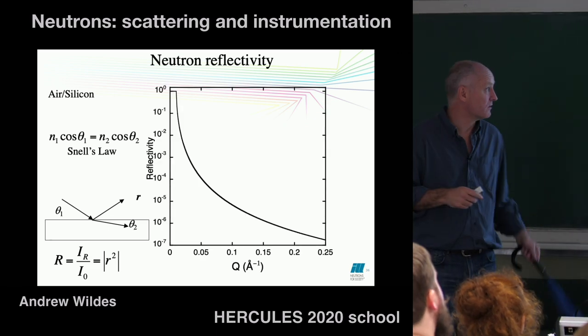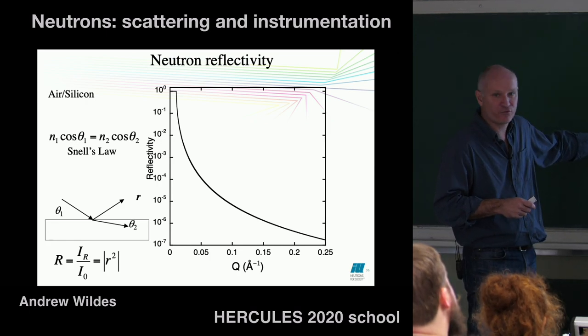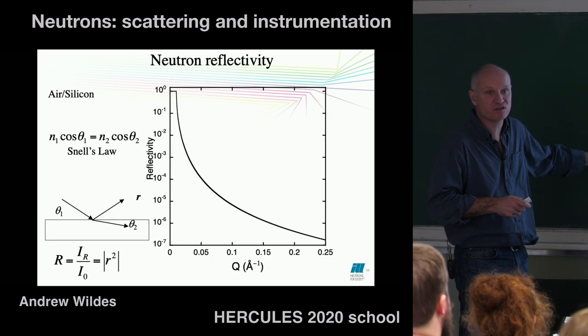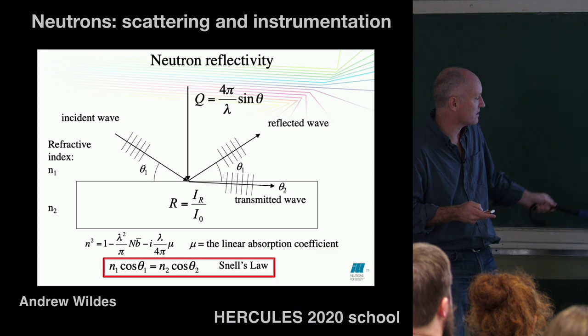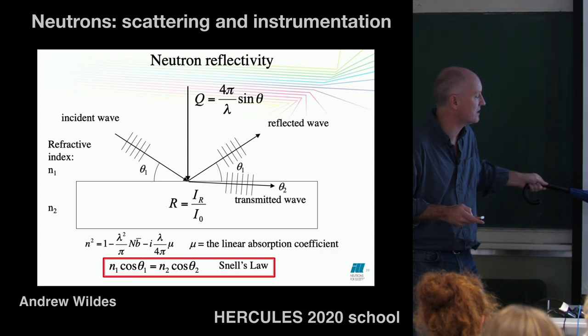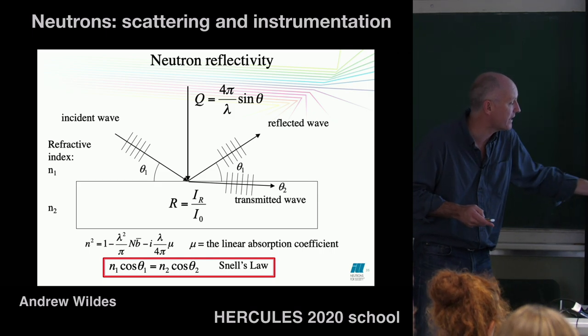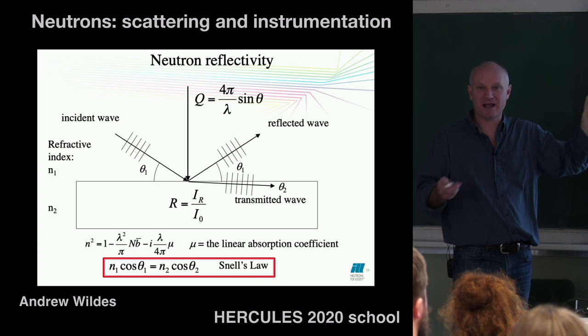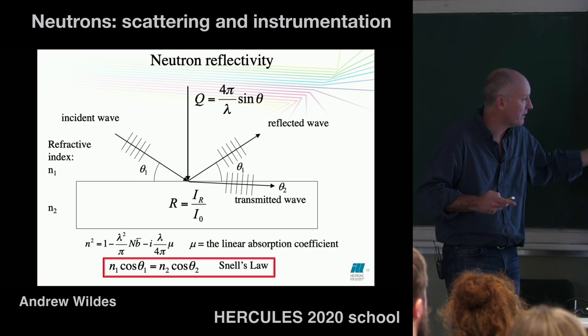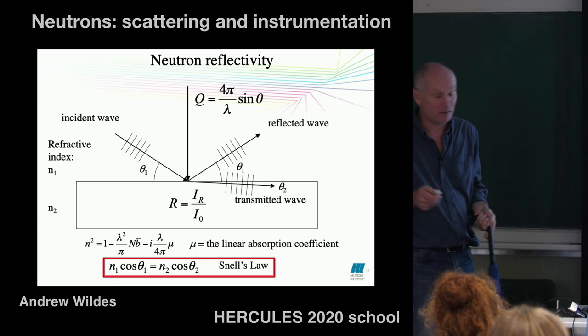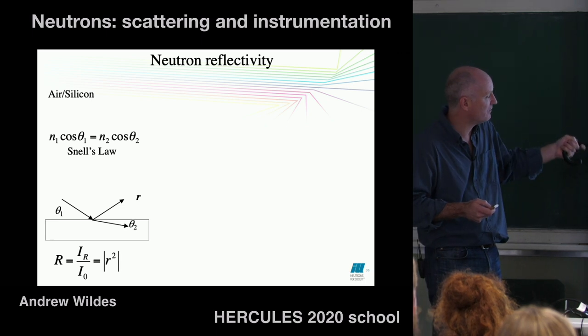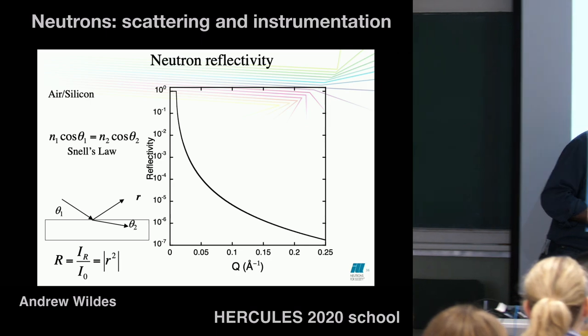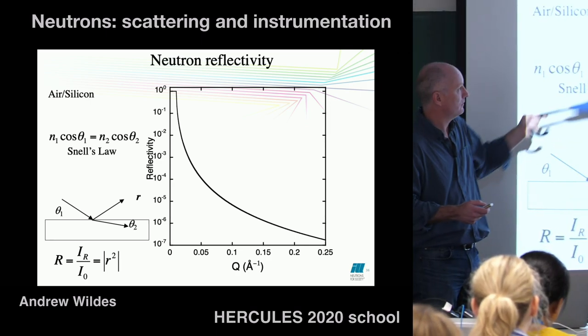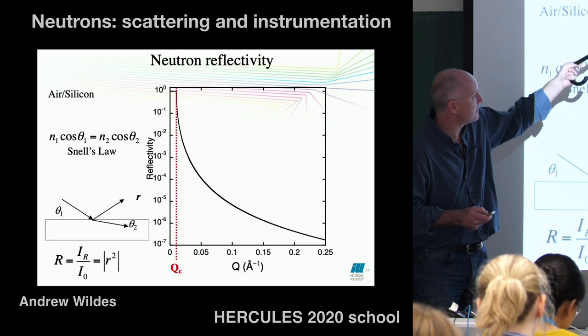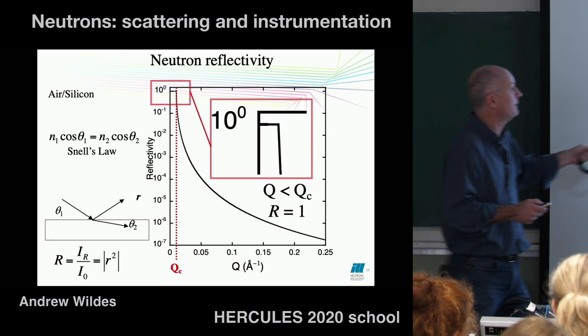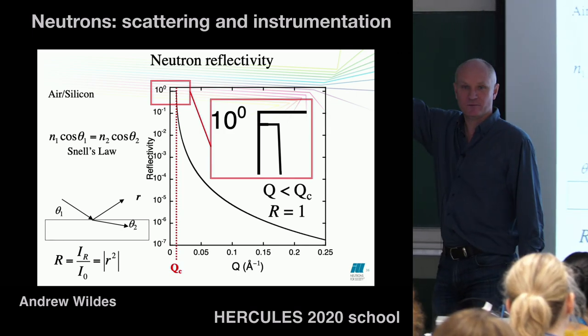What's very important is that this works if you go from a high refractive index to a low refractive index. This is important because the refractive index for neutrons and for X-rays is defined by this quantity here, and you'll notice that there's one minus some number. So if you take the refractive index for a vacuum or for air, it is one. And then you're going into a lower refractive index for neutrons and for X-rays. So if you keep that in mind, you're going from a high refractive index to a low refractive index, and you plot as a function of momentum transfer, you get a reflectivity curve. That's what it looks like. And if you look very carefully, right down the bottom here, you've got some sort of critical Q. You focus in on that, and all of the beam gets reflected. This is called total external reflection.